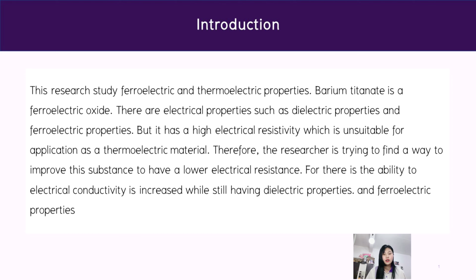There are electrical properties such as dielectric and ferroelectric properties, but it has a high electrical resistivity, which is unsuitable for application as a thermoelectric material. Therefore, the researcher is trying to find a way to improve this substance to have a lower electrical resistance, so that the electrical conductivity is increased while still having dielectric and ferroelectric properties.